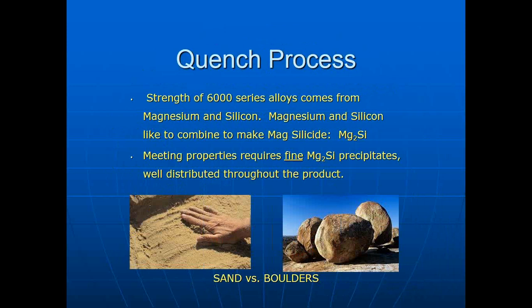If you have large chunks, that's a technical term, large chunks of mag silicide, they do two things. First, they rob mag silicide from the surrounding aluminum, which weakens it, and then they form a stress riser, so it's a place for the crack to propagate. So large precipitates are not desirable.